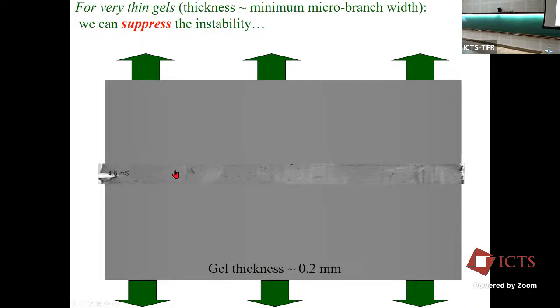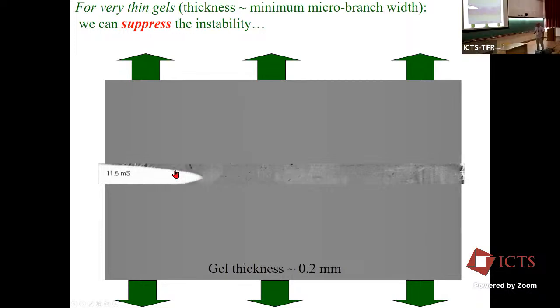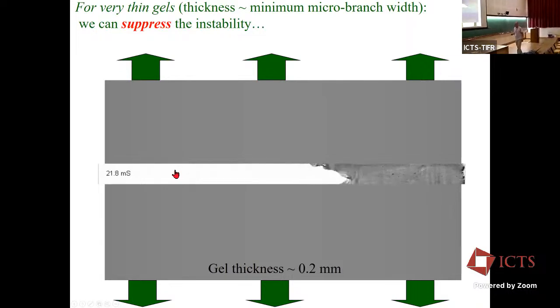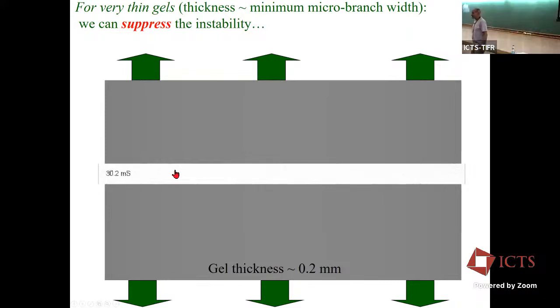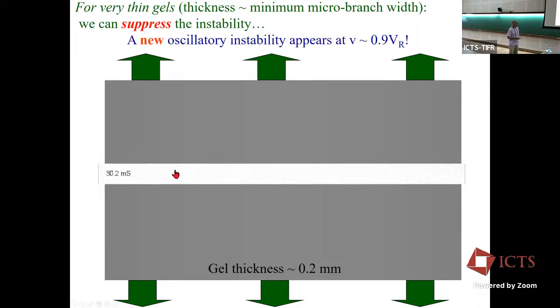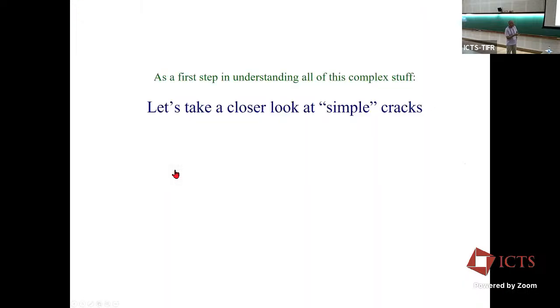So here's our crack. It's going faster and faster. Smooth, not branching, and then all of a sudden, at a little bit beyond the Rayleigh wave speed, it starts to oscillate and wiggle. This is one reason why I stopped doing theoretical physics, because my mind isn't fertile enough to guess this would happen. But if you just ask nature, nature tells you this is what I see, and then you have to think where this is coming from. So this is a new instability. It takes place at about 90% of the shear wave speed, 95% of the Rayleigh wave speed, actually.